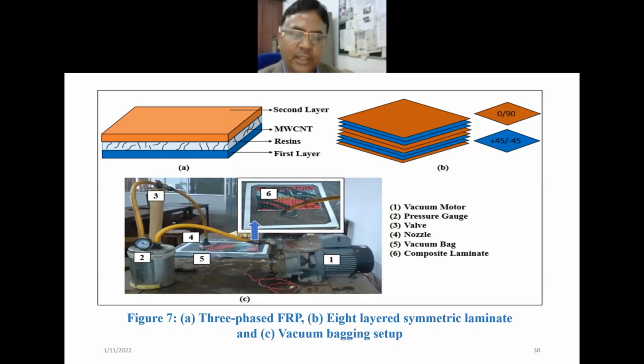how can we say the material we have made is good or bad? We cannot say this, because anybody can procure this material. So you can ask what is the fiber volume ratio for that. We have done testing for that, finding the volume fraction: put small pieces of this composite in the furnace, see the initial weight, burn it, see the final weight, and you can find out the fiber volume fraction of the materials in the lab itself.